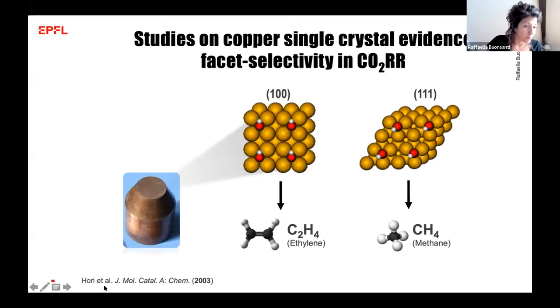A Japanese researcher, who has become quite famous by now, Hori, performed studies on single crystals, and what he found is that there is a structure-dependent selectivity of this reaction. In particular, that the 100 facet of copper produces more selectively ethylene, and the 111 surface produces methane. Now, normally, these studies on single crystals are performed in conditions which are not close to the actual conditions in which a device operates, and furthermore, single crystals cannot be implemented in an electrolyzer.